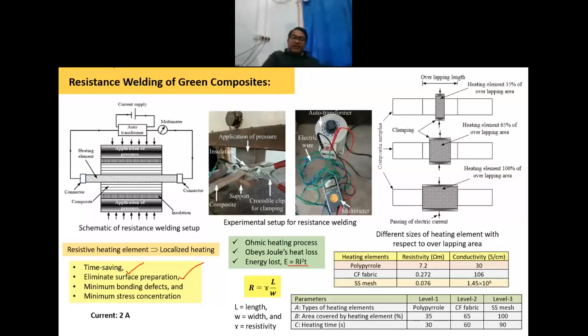So this is the setup that we have developed, and we have considered different parameters here. One of the important parameters is the heating element. We have considered three different heating elements: stainless steel mesh, carbon fiber fabric, and polypyrrole. All are electrically conductive, and it has to be electrically conductive. Stainless steel mesh is easily available. Carbon fiber fabric we have used as a heating element, and polypyrrole is a conductive polymer, available in powder form. First we created a polypyrrole film, and then we used that film as a heating element.